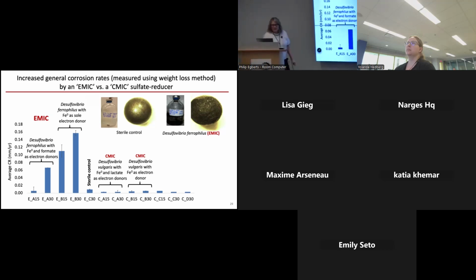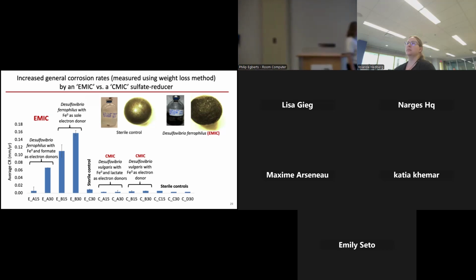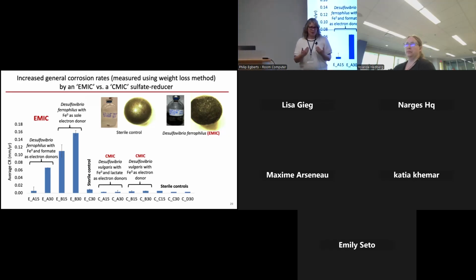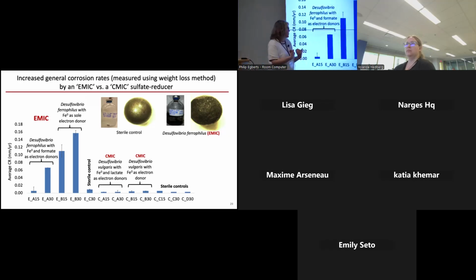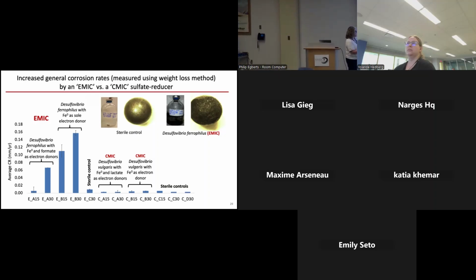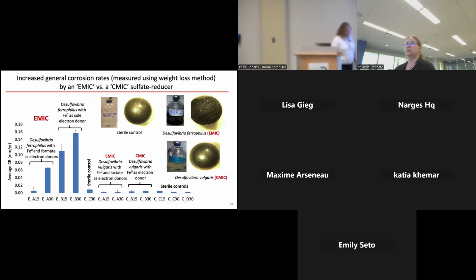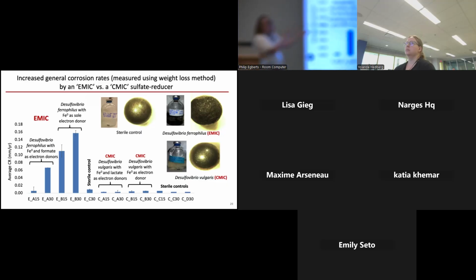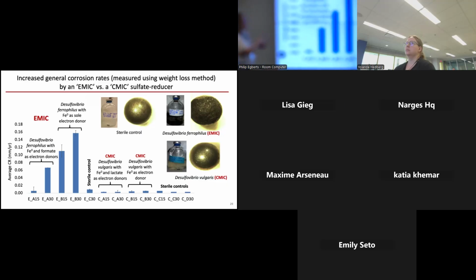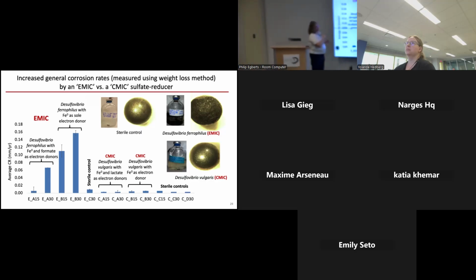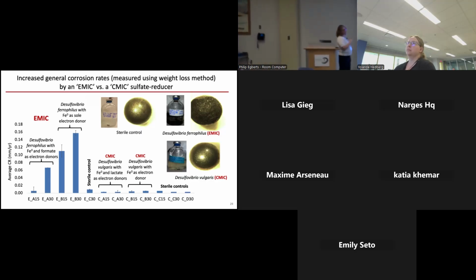And here on the bottom are the corrosion rates we got with an organism that is not known to use the metal directly as an electron donor, a different type of Desulfovibrio. You can see that the corrosion rates are a lot lower. And when we look at the beads, they're nice and shiny, just like the controls. So you can actually see some of the differences in the severity between the EMIC organisms versus the CMIC organisms.